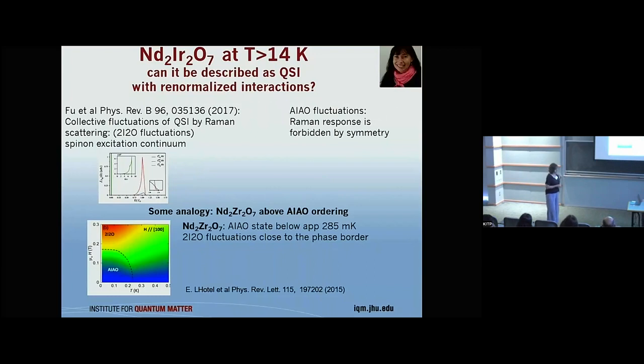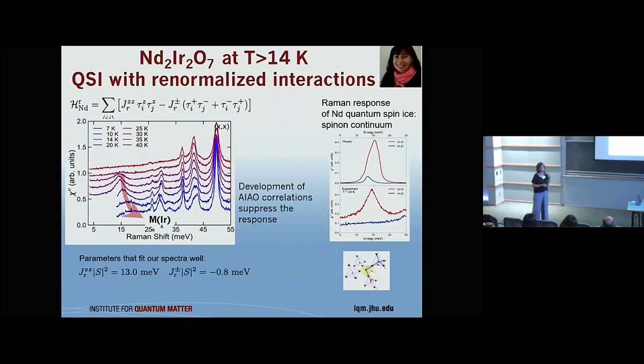So basically, we decided to be very bold and assume that what we see is the response of something analogous to quantum spin-ice. And Natasha and Yang basically took a Hamiltonian which would produce a quantum spin-ice and did some fitting to our spectra. If they take these parameters, which are pretty high interactions, then they reproduce the mode which we get in Raman scattering. I would like to argue that from an experiment this makes a lot of sense, because this mode is very sensitive to the development of all-in, all-out correlations between neodymium moments, which we know from other measurements, like even specific heat.